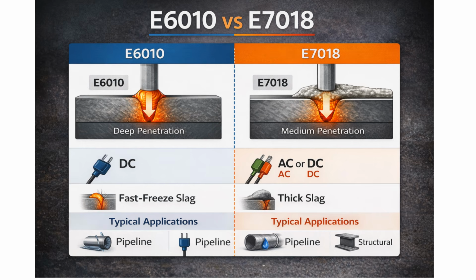E7018. This is probably the most popular low-hydrogen electrode in the world. It runs on AC or DCEP, deposits a smooth bead with excellent mechanical properties, and is required by many codes for structural and pressure vessel work. The iron powder in the coating gives a high deposition rate. Remember, these must be stored in a rod oven at 250 to 300 degrees Fahrenheit to prevent moisture absorption.